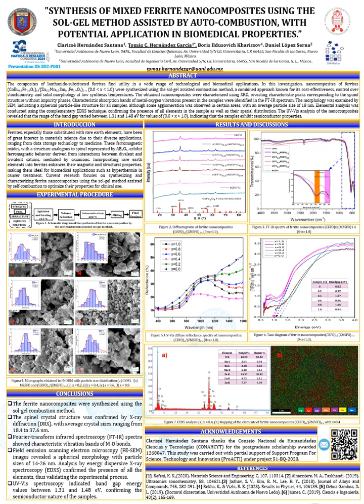Energy dispersive X-ray spectroscopy, EDXS, analysis confirmed the presence of all elements, thus validating the experimental process. UV-vis spectroscopy showed bandgap energy values between 1.31 and 1.48 electron volts, confirming the semiconducting nature of the samples.